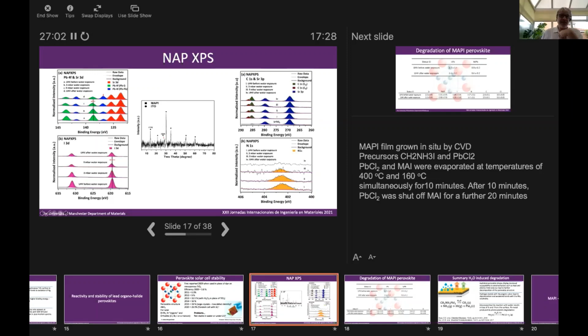The iodine is similar. We see as we increase the water vapor pressure, the peak energy decreases, and again is consistent with formation of lead iodide, and also the intensity of the peak falls away. Carbon is not so interesting. We've basically got some hydrocarbon contamination on here, which is the green peak, and the red peak is the methyl ammonium in the perovskite. When we expose to water, we see a shift in weight to this hydrocarbon peak. So again, this is pristine MAPI, 3 millibar, 6 millibar, and again after the exposure to water.